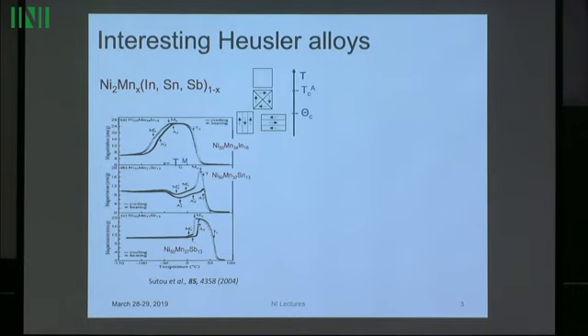Recall these diagrams where I put the temperature axis vertical. Then we have a Curie point for the austenite phase. That's where we begin to see magnetism. It's a second order phase transformation. And then it could transform by a martensitic phase transformation to a martensite phase, which may or may not be ferromagnetic. I was discussing the sensitivity of magnetic properties to the lattice parameters, which change here, meaning that many different possibilities could occur.